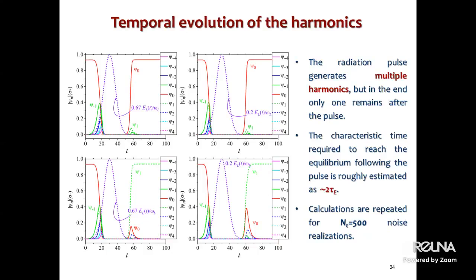The characteristic relaxation time to reach equilibrium after the pulse is of the order of 2 tau_E. So pulses of this size, and then superconductivity starts to grow after another decay time. This is for a particular noise realization, but in the simulation, in order to obtain the probability, 500 noise realizations were used, which enabled us to extract the probability distribution of a final state.